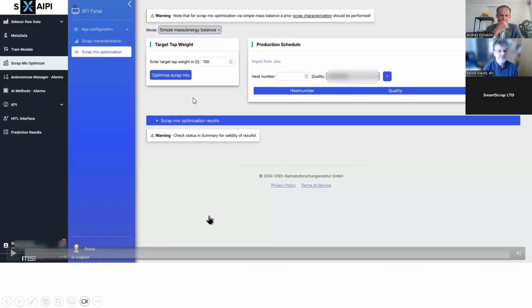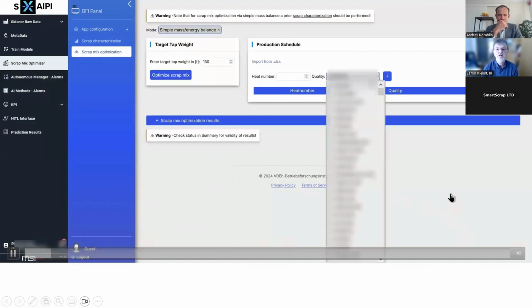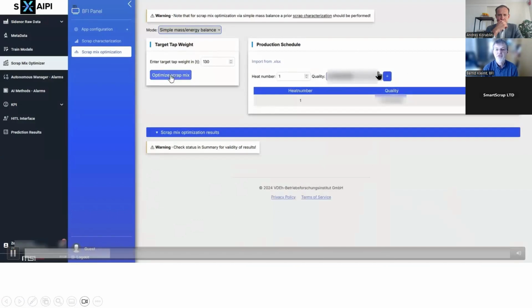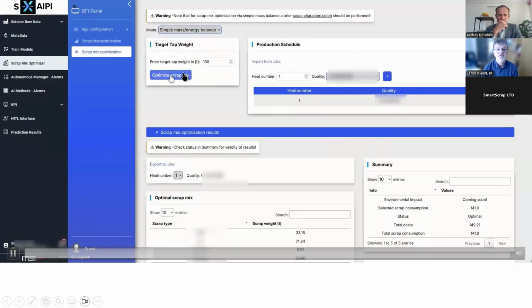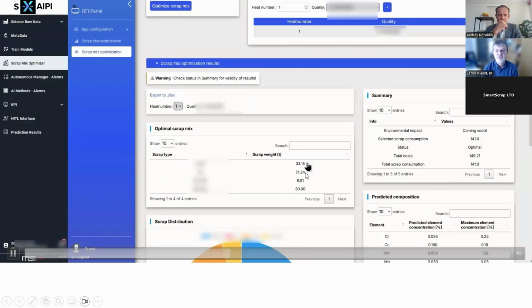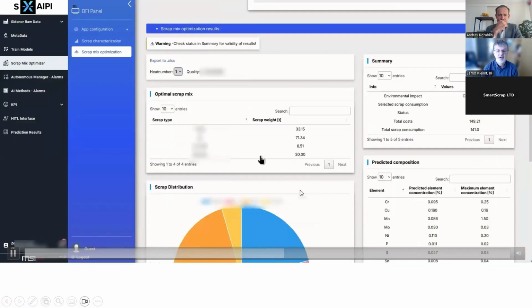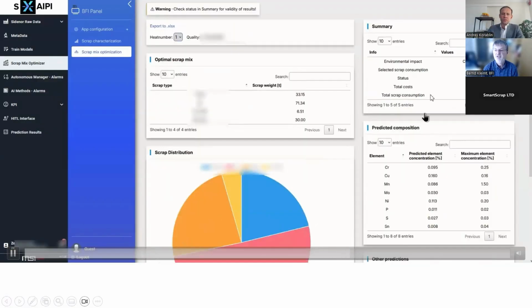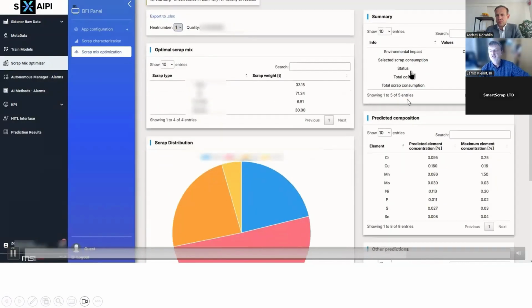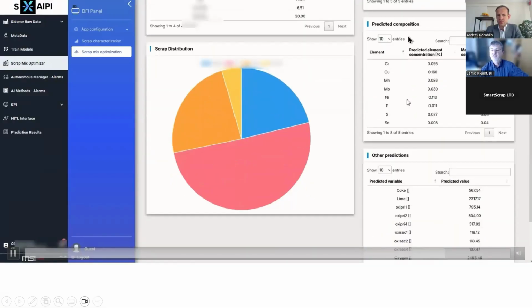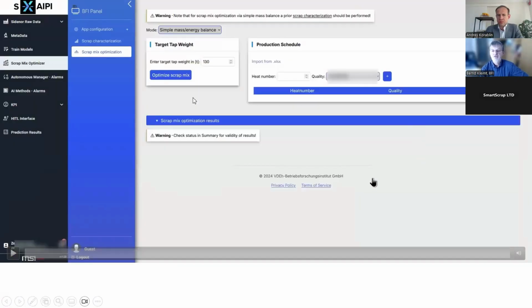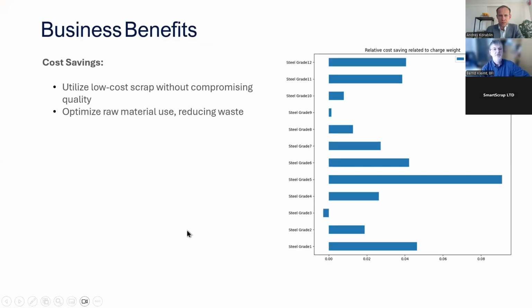So this is a very short video to show how the scrap mix optimization works. I will just let it run. You see here, you select the quality which has to be produced, start optimizing the scrap mix, then you will receive the result, the different amounts of scrap to be charged for the different scrap types in use. And on the right-hand side, you will see the result, the total costs, the predicted element concentration, and also further information, how much oxygen has to be used, how much lime, and so on.